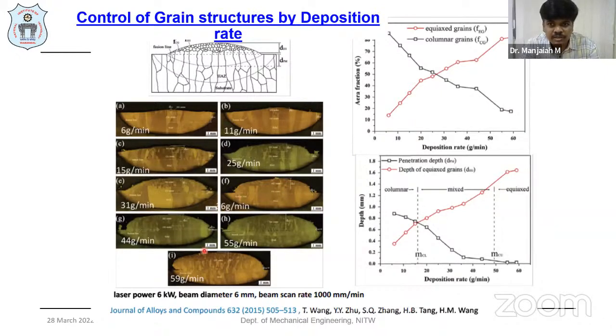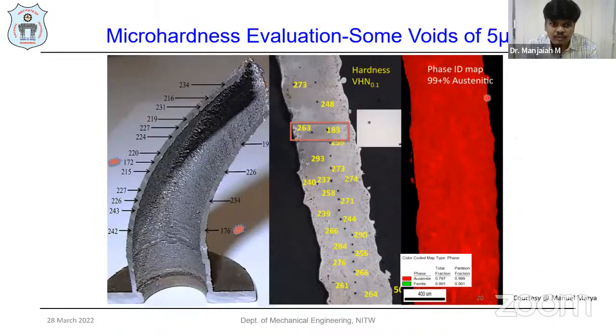And you can see the area fraction varies with respect to the deposition rates. You can also control the equiaxed grains by controlling the energy density and the cooling rate. If you measure the hardness properties, hardness is almost the same throughout the fabricated component, but there are some voids less than 5 microns. These are the key voids, that is, the porosities.